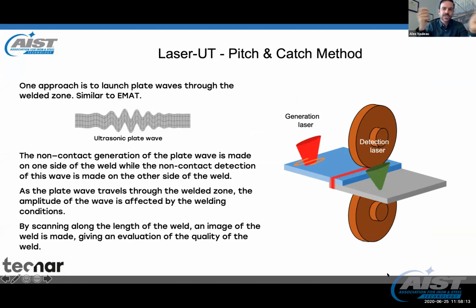One is what we call pitch and catch. Pitch and catch is what would definitely be used for laser butt or keyhole welding, because it's not relevant to just scan on the weld itself. You're just going to pass sound through it, like the EMAT product would. So pitch and catch is laser on one side, detection laser on the other, and we just send the sound through it. It's going to measure the whole volume of the weld. It's going to backscatter. It's going to attenuate if there's any porosity or lack of fusion.